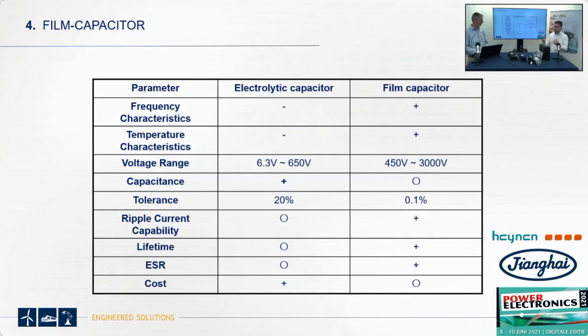And this is what I explained before. You close the holes inside the foil, and then at the end you have only the same thing like the film capacitors, only two plates and in the middle one big dielectric. So a very low capacitance. Very low capacitance, and then you have a much more expensive capacitor with no better behavior than film capacitors.